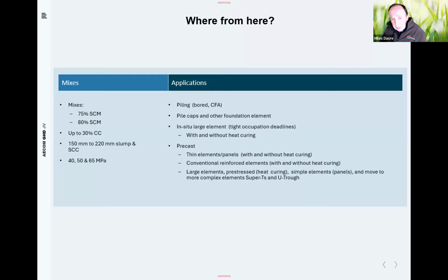So there's a lot of positives in going this way and getting the industry to move more towards these types of mixes. And we believe that calcined clay might make self-compacting mixes more robust, for want of a better word, because that's been the previous issue when self-compacting mixes first came into the market in Australia, because of their sensitivity. DOTs and major projects were a bit concerned about the quality control and the ability for segregation to occur. So there are some real benefits that these top-line calcined clays are bringing that we've got to unlock very quickly, but should be able to solve what we think are the main issues preventing decarbonisation of concrete across the board, which is really exciting.